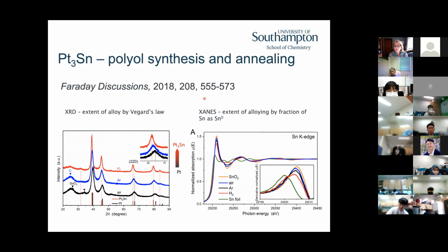Okay. So the first of the samples that I promised to talk about is platinum tin. And we started looking at this by making a platinum 3 tin material using the polyol synthesis method. So we made a family of samples, and this was done by a postdoc in my group named Abu Nassar and a PhD student named Haolong Huang. And we made these samples by using the polyol synthesis. So we take the parent sample and we anneal it differently.